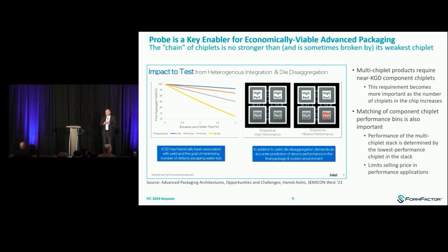On the right, a more subtle but also very interesting implication of chiplets. I think of it as a lowest common denominator principle. If you're going to package different pieces of silicon together, the matching of their performance levels is pretty important, right? You can imagine that if you're packaging 3 high performance die together, as in this example, with 1 lower performance, the system's only going to operate as good as its weakest link. And so that's also driving up test complexity to do things like at-speed test at the wafer level, to do components of system-level test at the wafer level, where there's some degree of memory and other active circuitry on the probe card, at least for a SoC die test, to really exercise all the different failure modes and make sure that you have matching across the overall chiplet stack and each component.